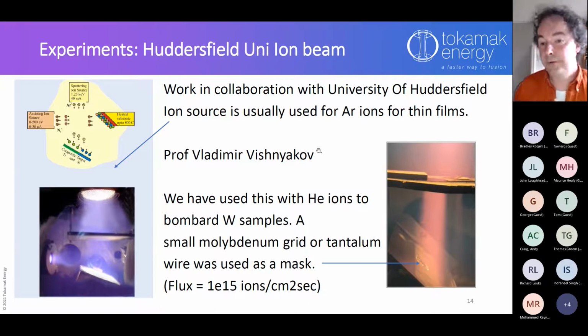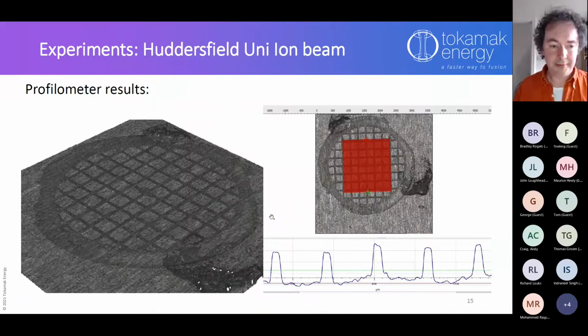What I've been doing is exposing them to ion beams, because in our plasma we basically have ions of helium, hydrogen and hydrogen isotopes. At Huddersfield University they have an ion source, which is kind of shown here, but we've been focusing it and collimating it. As you can see here, this purple beam is the ion beam, so this is helium ions. They're zapped down to land on a sample, which is placed down at the bottom, and we mask it with a molybdenum grid. The idea of that is that you end up with a sample like this.